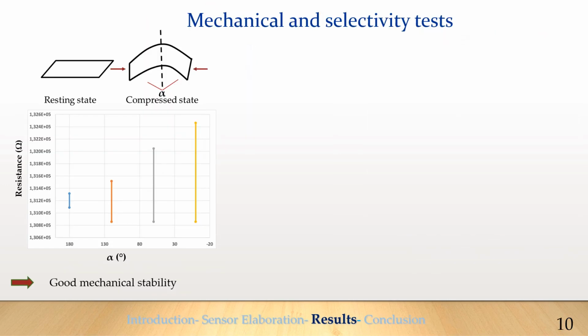Mechanical stability tests were performed to verify possible distortion of our flexible gas sensor that may occur during the resistance measurement, which in turn may lead to error of gas concentration measurements. So, like we see in this graph, the resistance of the sensor shows very negligible changes at different bending angles compared to the resistance change in the presence of the gas.